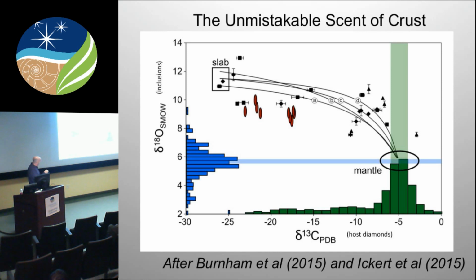The inclusions, and I'll show you some of these inclusions momentarily, that we've looked at, and the diamonds that they're in, form this kind of array. This is where the slab would be, this is where the mantle would be, and these are mixing lines between those two. And again, we can see clearly indication that the inclusions and the diamonds themselves are subducted. They're recycled subducted material.